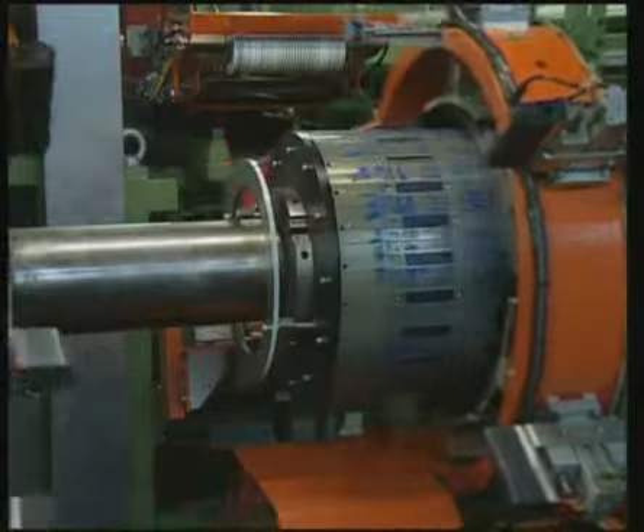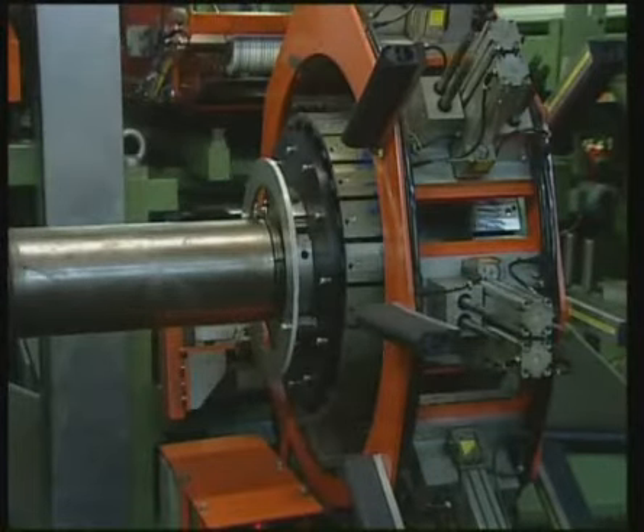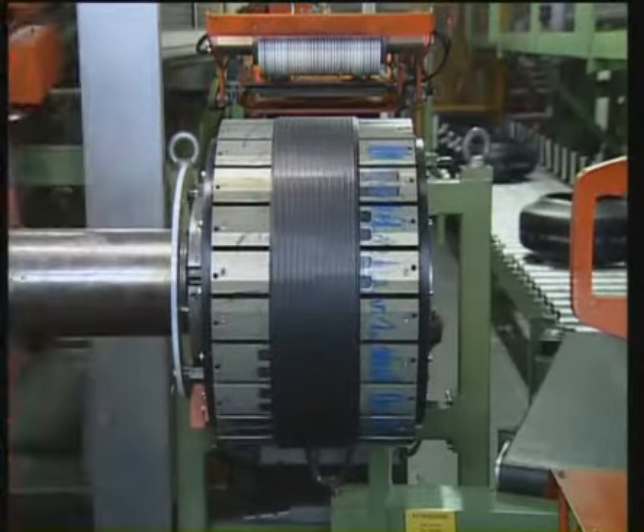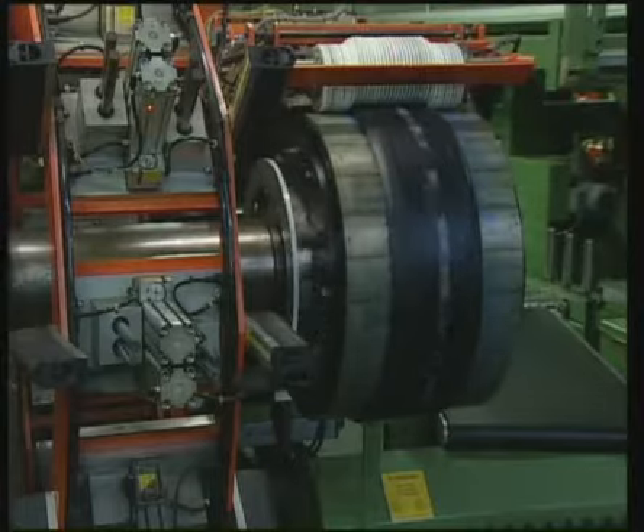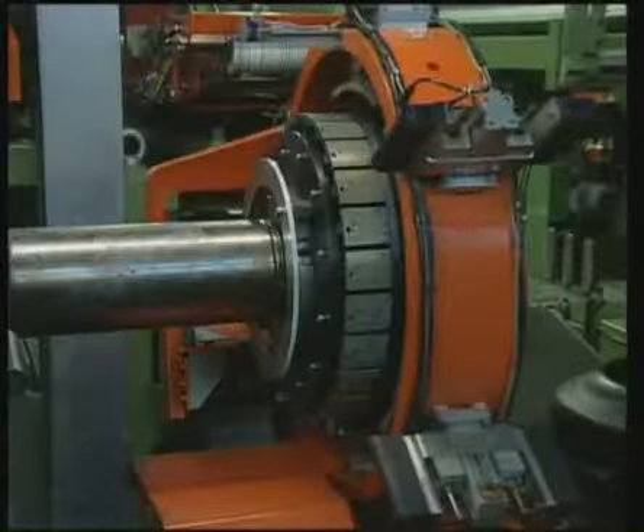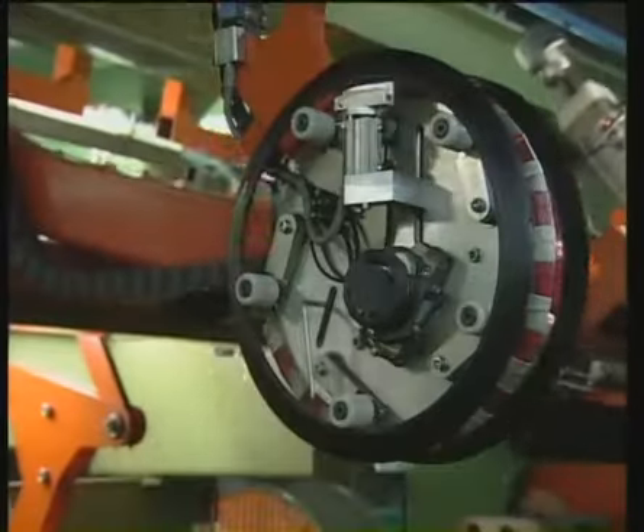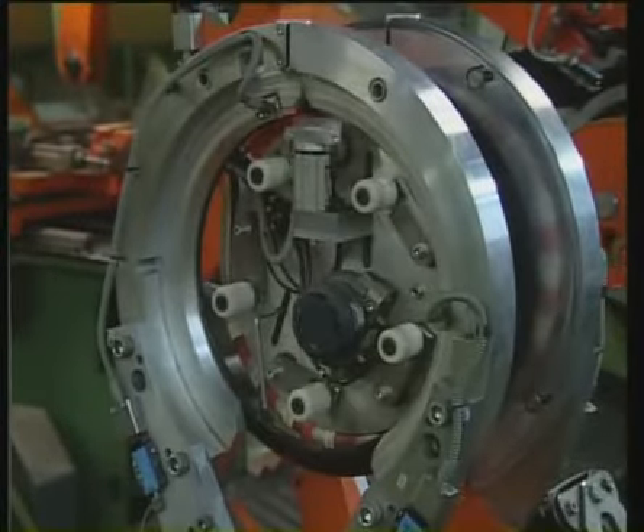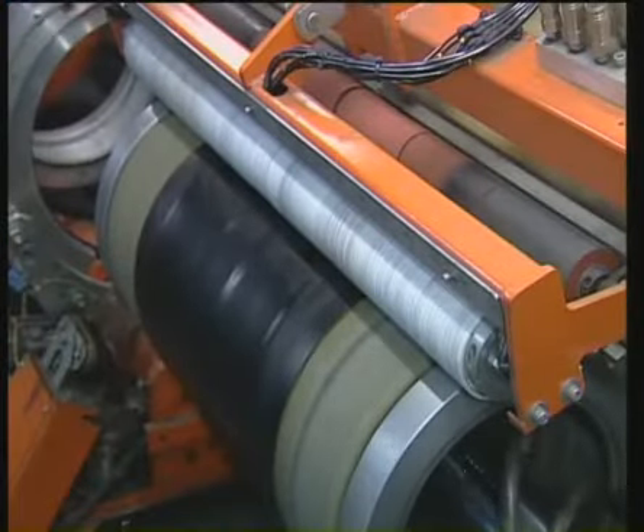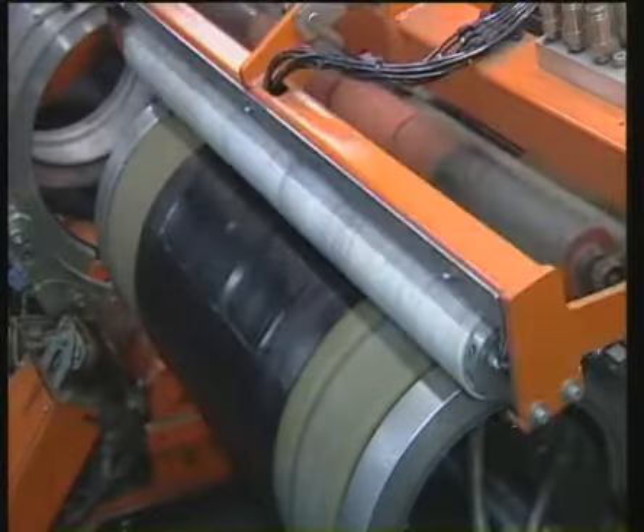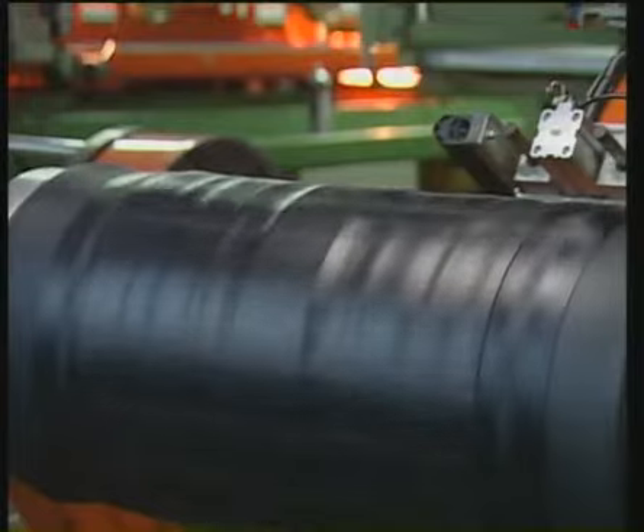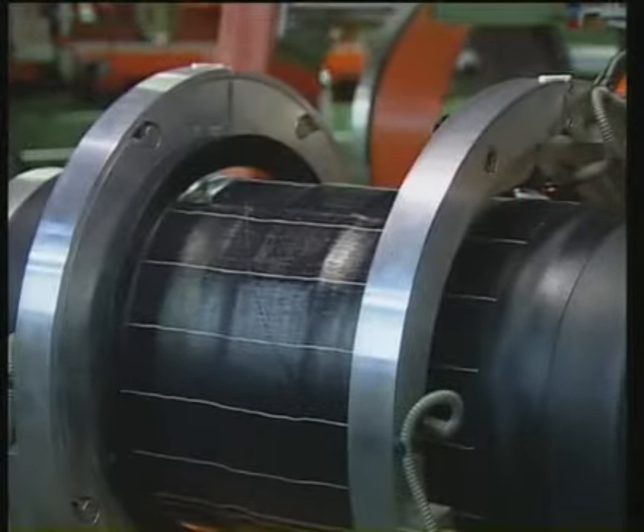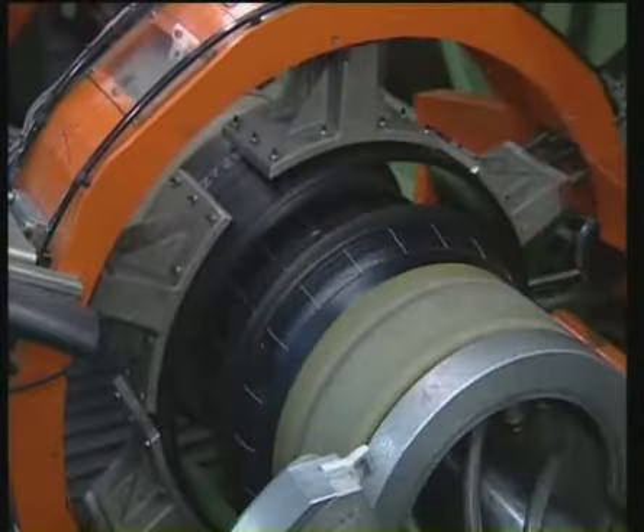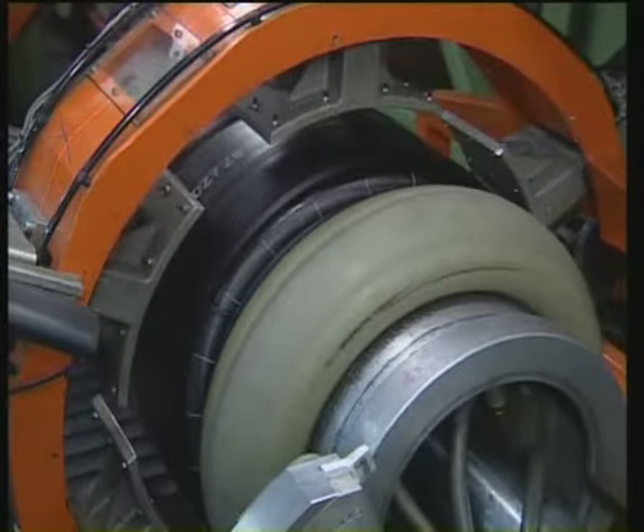Assembly is performed on two separate rotating drums. The first drum places, in sequence, the two metal belts, the nylon spiral belt and the tread strip. The result is a sort of ring. The second drum, on the other hand, is wound with the liner, the sidewalls, and the rubberized fabric that makes up the casing. The result is a cylinder, onto which the bead wires are positioned. The final phase in the operation involves joining the ring and the cylinder, creating the final shape of the tire.